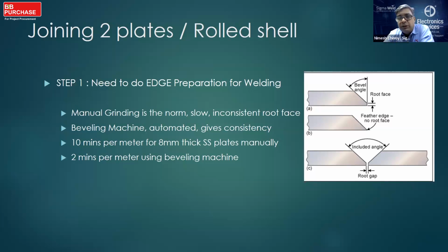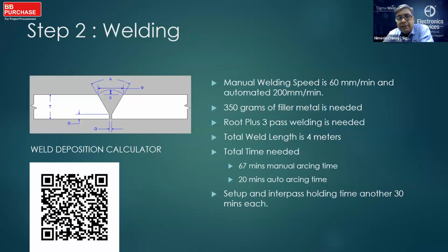By doing this, you will always be able to save time. So for example, if you're using manual grinding for an 8 mm thick stainless steel plate, you would require something around 10 minutes. But if you did it with a beveling equipment, you would do it in under 2 minutes. So the first thing, if you do it with an equipment, you always get consistency and you save a lot of time. Second, once the edge is ready, you need to weld.